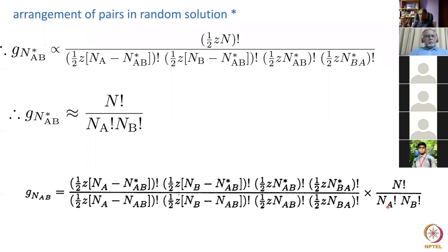So that's quite a lot to take in, but the principles are straightforward so far. In our partition function, we have simplified the problem by taking the largest number of NAB bonds, and ignoring the number of configurations for all others. And in this process, because we can't treat pairs of atoms as being completely independent, if this was an equation, it would overestimate. So what we are doing is normalizing the general equation for the number of AB bonds by these terms here, which are equal, just dividing at the bottom by this and multiplying by this.